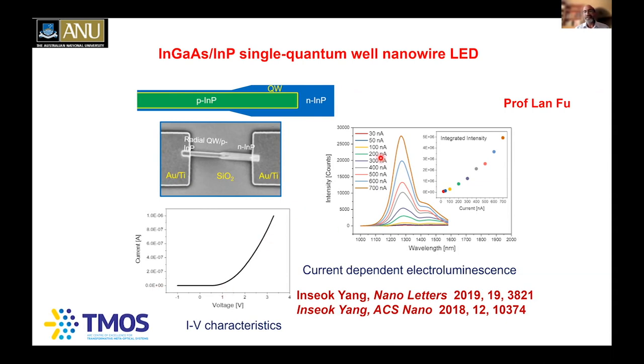And as you're injecting more and more current, you see very bright light coming out of these ones. And you also see two emission peaks. One is coming from this top quantum well, or axial quantum well. The other light is coming from this radial quantum well. And you can see these are emitting in this 1.3, 1.55 micron wavelength region. That's the wavelength region which we're using for optical fiber communications, which I told you.